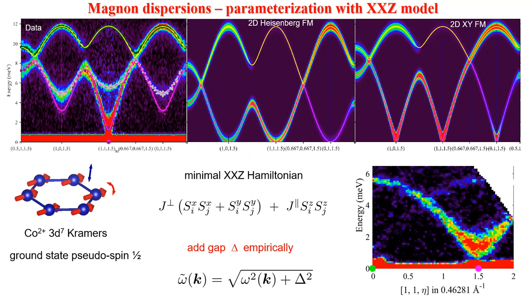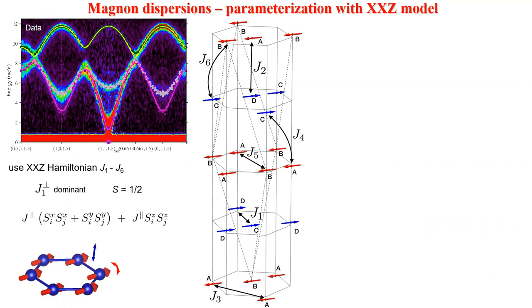So if we add a constant to the Hamiltonian, it would essentially only modify the spectrum at low energies and leave the rest essentially unchanged. So we include the nearest-neighbor coupling, which involves super exchange between cobalt, oxygen, cobalt, and then we also include all